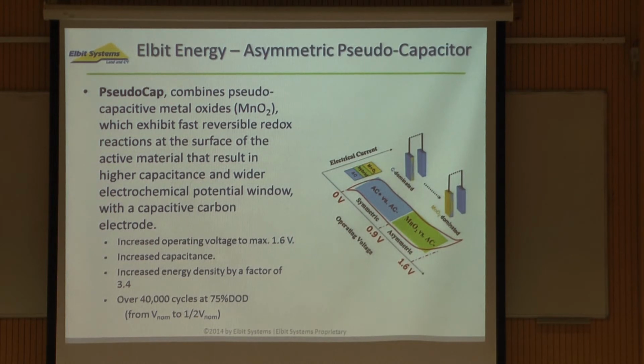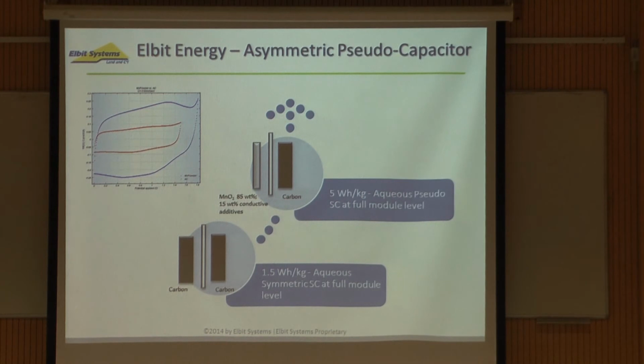This is why the supercapacitor has the capability of providing 1 million cycles and a long lifetime in comparison to batteries, where they have these redox reactions that actually somehow degrade the behavior of the electrodes, and that's why their lifetime is lower by orders of magnitude. So what we did, we implemented this asymmetric configuration, and instead of having 2 carbon electrodes, we had this manganese dioxide electrode coupled with a carbon electrode, and this is what we achieved in terms of the capacitance.